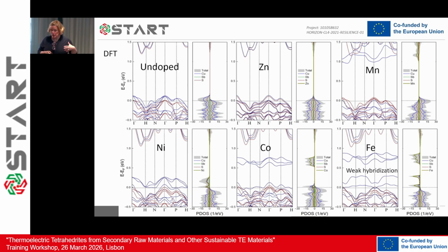So the materials are quite conductive, except for iron, because with iron, when you replace 1, you have these very localized states that tend to decrease electrical conductivity because they work as carrier scattering. So the conductivity with iron is much less.